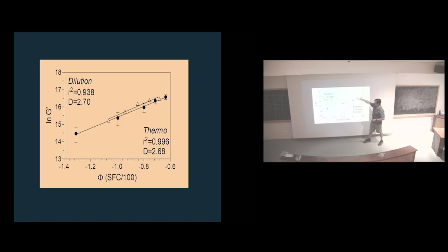And we found that both the dilution method and the heating method, the other one is complicated, the dilution. You have to create dilutions, right? Make a whole bunch of samples, measure the samples, very controlled geometries. We have all these nicely controlled, if you need them, 3.2 millimeters by 2 millimeter size pieces in which we crystallize the fat so we'd have no funny shape effects. And basically the slope that we get both from the thermomechanical method and the dilution method were the same.